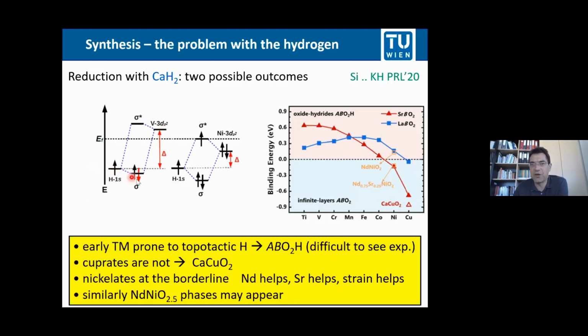The electron of the hydrogen goes into the bonding pair, and you can even put a second electron from another vanadium d orbital here. So you gain energy. That is why we gain energy here. However, in the late transition metal oxides, these z-squared orbitals are already occupied. Now, if you bind hydrogen, you have again bonding, anti-bonding, but now you gain some energy and you lose some energy. And for the nickelates, it's pretty much balanced. And for the cuprates, you lose energy in the process. That is the physical understanding behind it.